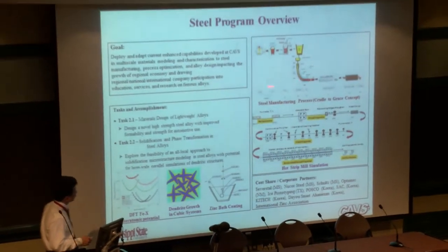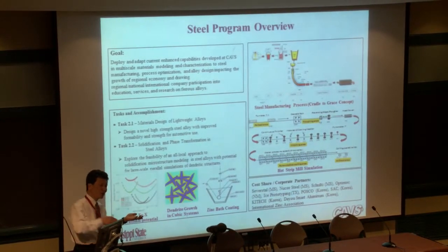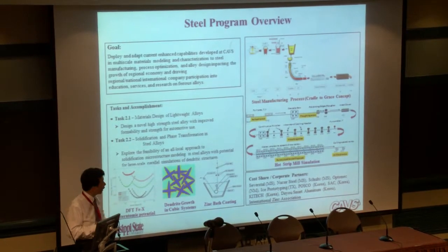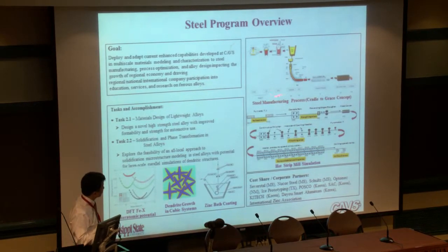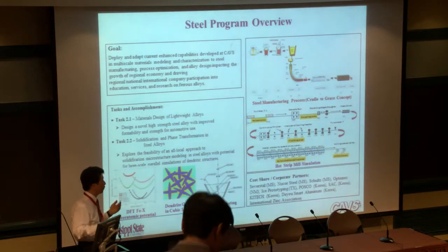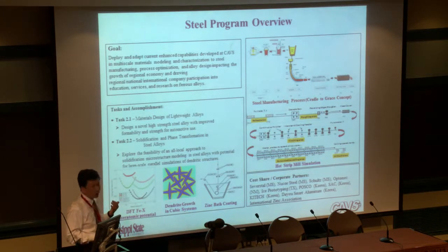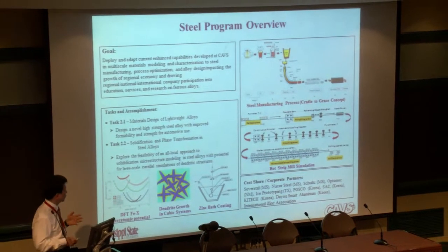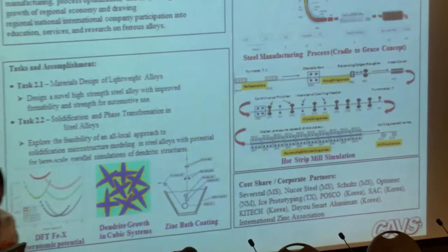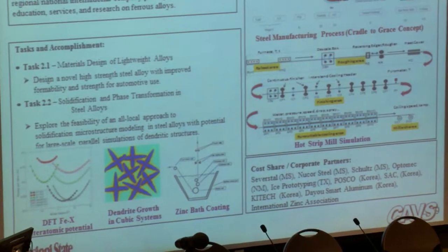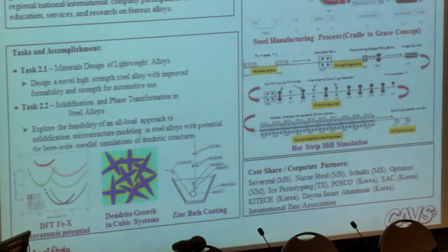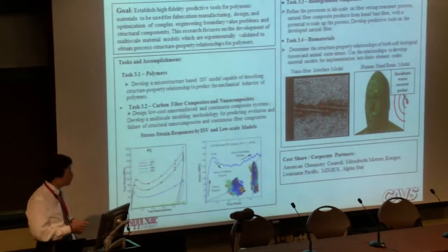The interesting part is that in our backyard, we have a twin roll caster with a sheet product. It's only 10 minutes driving away, and they've been working with us for the past 2 or 3 years. We try to understand what they're doing, as well as they try to show us what their need is. For example, a dual-phase alloy in the higher grade, and a TRIP alloy, and what the application is. So we start getting into not only the steel manufacturing, but also the process, what kind of software code, and how our multi-scale work can help enlarge that existing software, which we call metallurgical code, and whether we can enhance it with detailed information and modeling. So that's a steel program.